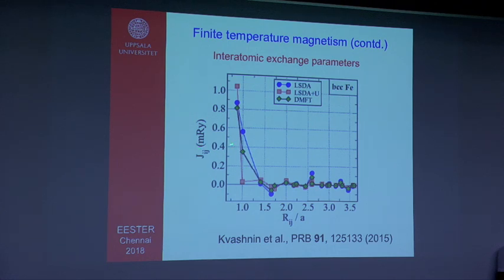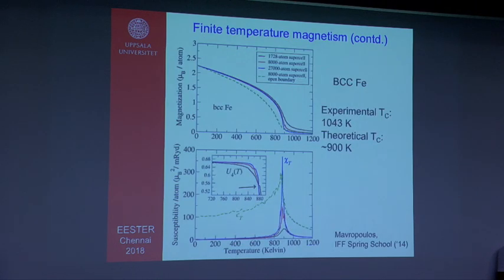So once again, the J is positive, means this is the ferromagnetic regime and this is the anti-ferromagnetic regime. So now once you have these exchange parameters calculated from DFT, then you can proceed towards Monte Carlo simulations, and you can get curves like this. So this is the magnetization versus temperature in Kelvin.